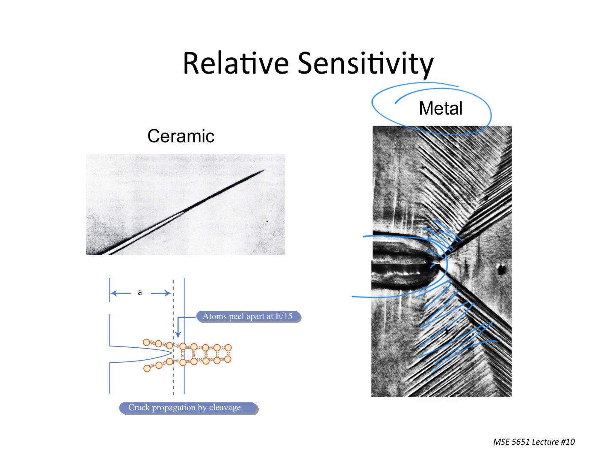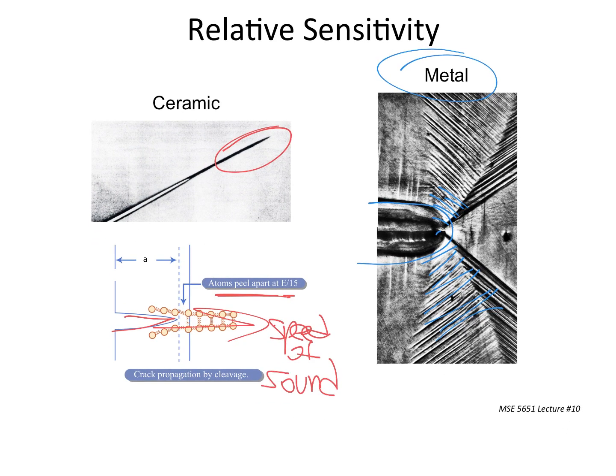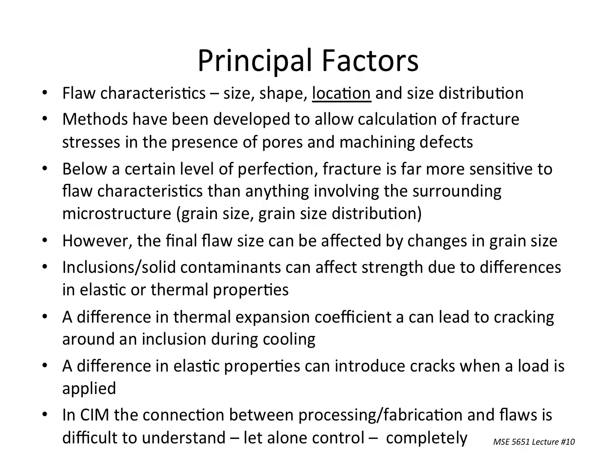It has not failed. With ceramics, you have, unfortunately, again, the very sharp flaw, and these atoms will peel apart at about a 15th of the modulus, meaning that this crack gets going and then it moves at the speed of sound after that. And that's how these things break like glass in vivo, because there's just so much energy involved, and there's no resistive mechanism. It doesn't generate dislocations, unfortunately. And so these flaws, as I keep hammering you with, are deadly, more or less, depending. They literally could be deadly.